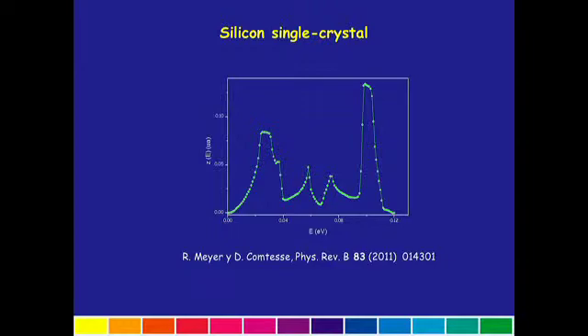If we have a polycrystal, we have a different cross-section. The cross-section we calculate is not useful, right? But for a single crystal, we can suppose that only incoherent scattering is going to take place, and we can work only on that. Incoherent approximation is good for that, and that's what we did. What we needed was to know the frequency spectrum of the silicon, the single crystal silicon.